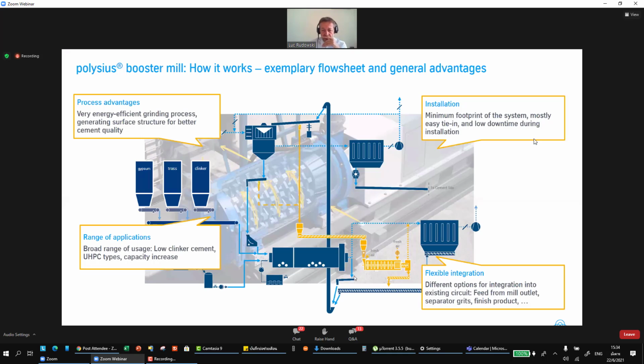So the system here, as you can see, the booster mill with the feeding system here, can be fed either by the product outside the bucket elevator, the mill outlet, let's say, or from rejects from the separator. And the objective is to get a feeding granulometry into the mill of less than 500 microns or 0.5 millimeters.